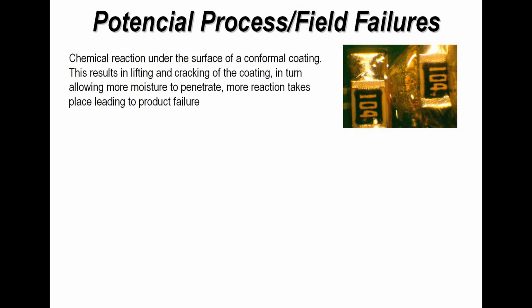Another example of cracking and chemical reaction is illustrated in this photograph. What has actually happened here is something underneath the coating has allowed a reaction to take place, which has then caused the conformal coating to crack. In that situation, obviously, the coating is lifted from the surface of the printed circuit board, and a reaction has taken place, and this will continue to occur.